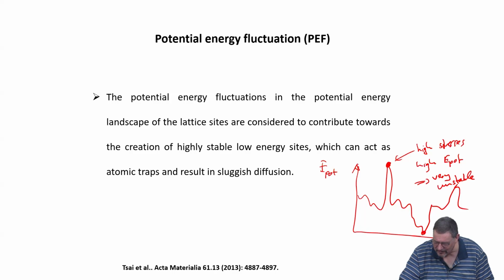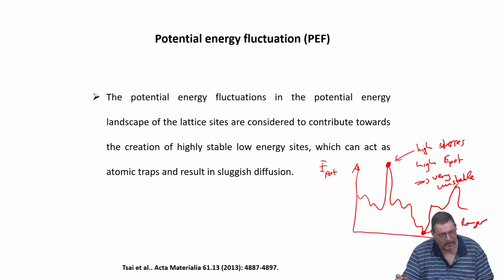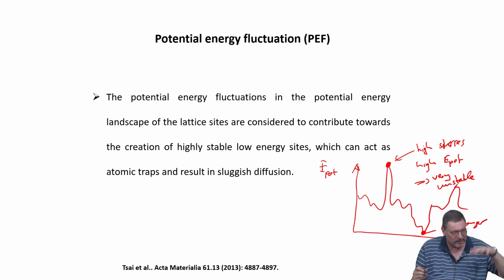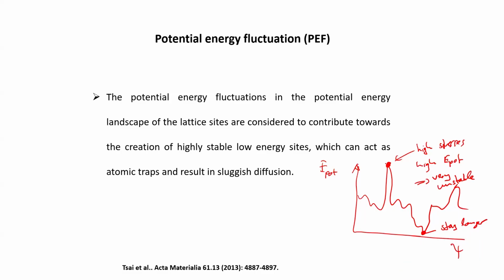This guy here will stay longer because it has more bonding strength, because the potential energy is lower. It feels well where it sits. And this guy here will jump faster because it's in such an unfavorable position, so any small additional kick by energy just coming from the environment will put it into the next position. And so this is affecting diffusion. Slow diffusion, sluggish diffusion would be these guys.